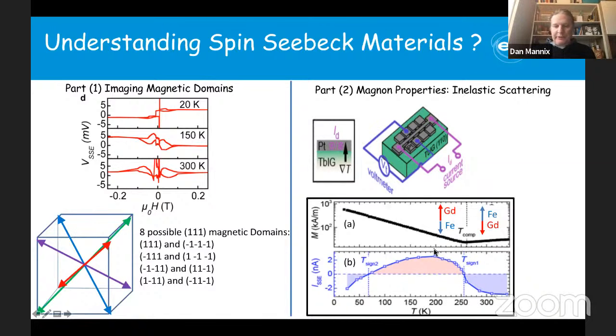It's not quite well understood, but there's another sign change at lower temperature, which doesn't seem to be related at all to the magnetization. So the question is why? What is the origin of that effect? And because the spin-Seebeck effect is believed to be due to the magnon properties, what we wanted to do is characterize the magnon properties and see if we can get more information on this second sign change. So that's really the second part of this talk.